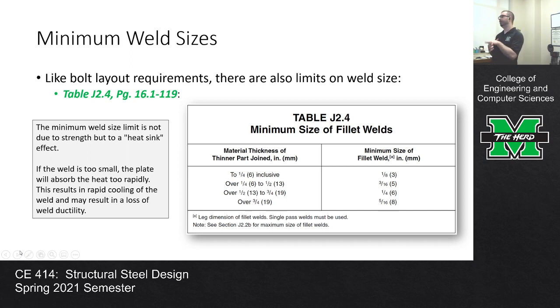So I take the two plates, and when I say plates, again, I keep using that term pretty loosely. Plates could be just a plate of steel. It could be a flange of a W shape. It could be a web of a channel, just any flat piece of steel that's being welded to another flat piece of steel. I take the thinner part, whichever part is thinner, and I look at this table and I say, okay, if the thinnest part is 5/8 inch thick, then the weld needs to be at least a quarter inch. That's the weld size. And we tend to spec weld size out in 16ths of an inch. So the weld size is 1/8 of an inch or 3/16ths or 1/4 or 5/16ths, et cetera.